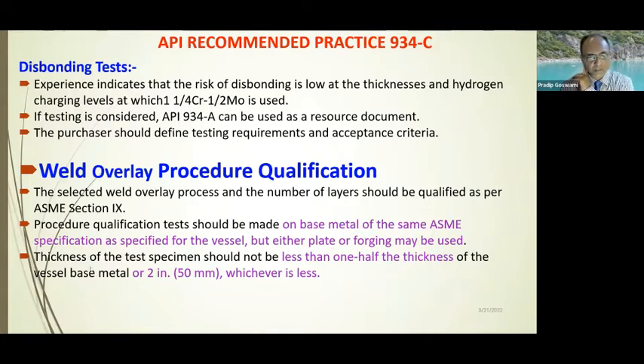And the thickness of the test specimen should be typically 50 mm or 1/2 the thickness of the base metal, whichever is less. So typically if it is 4 inch, that comes to 100 millimeter, or it could be 2 inch or 50 millimeters. You need to take the lesser of this thickness, particularly for the qualification of the coupon for weld overlay. And I would say that typically 2 inch or 50 millimeter is a ballpark figure which is generally recommended or generally adopted.